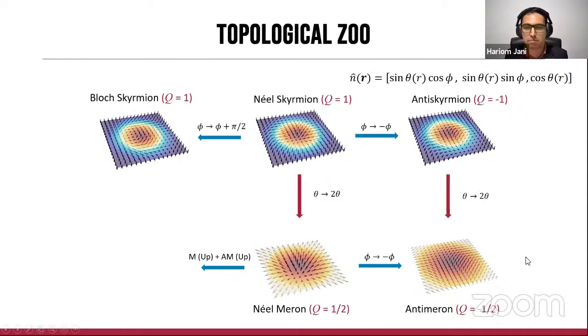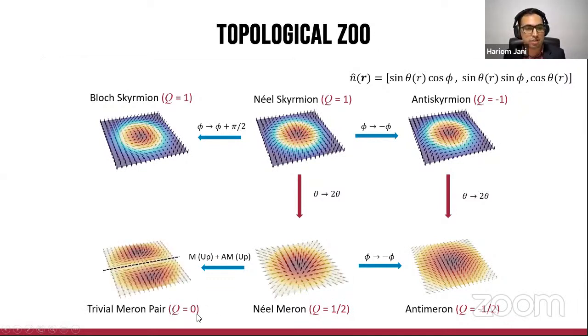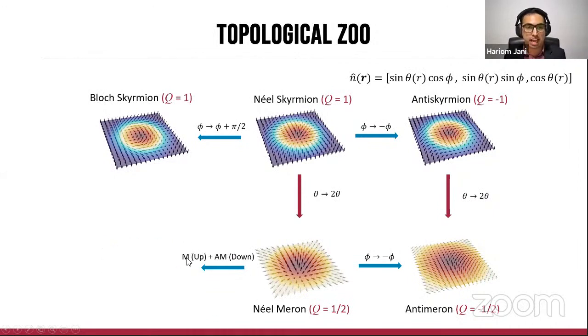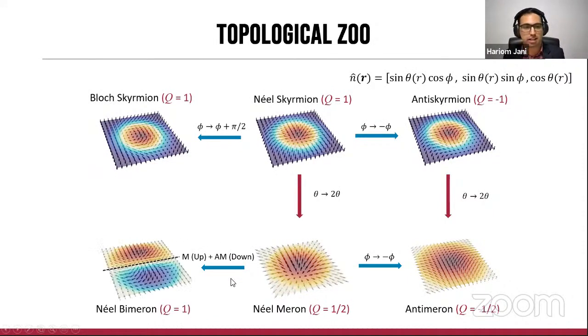So for example, if we take a meron and antimeron with both their cores aligned, as you can see, their topological charge is +½ and -½, they would actually constitute a trivial pair as shown here. If, however, we have a meron up, antimeron down, for example, then we have +½, -½, and that would actually constitute a topologically non-trivial object, which is called a Néel bimeron. Various other combinations can also be achieved, and you can also have Q = 1 or -1, depending on how these permutation combinations are realized.